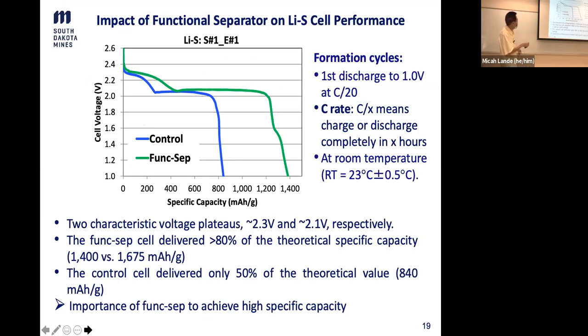Again, we have the plot of cell voltage versus specific capacity, or voltage profile. We can see that the advanced cell shows this nice two plateaus here and here. The lower plateau is the one that contributes most of the capacity, so it's long. And then we measure at the end of discharge what the specific capacity is.